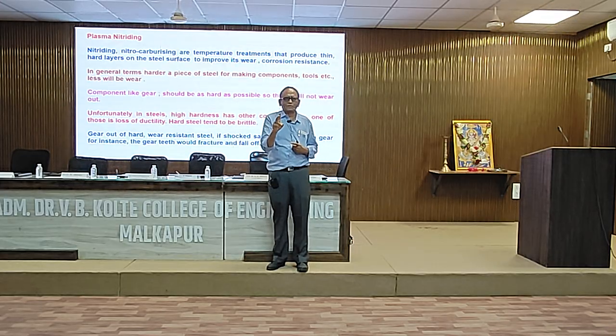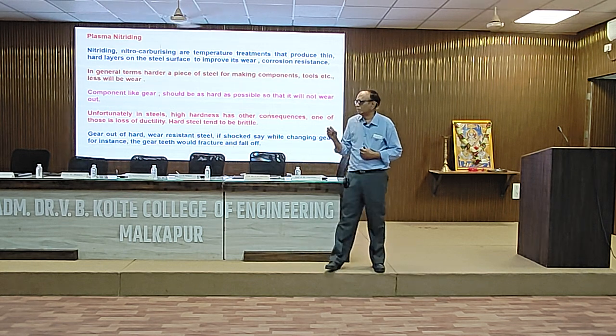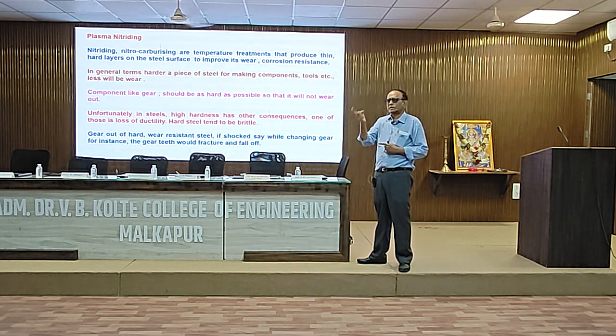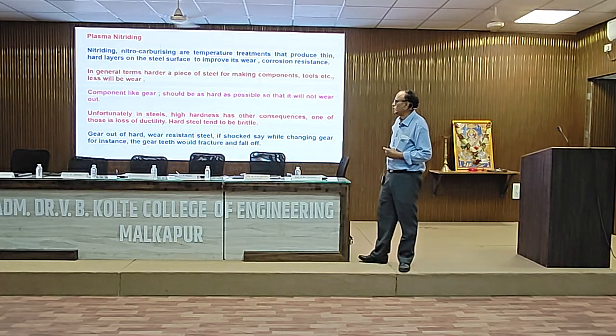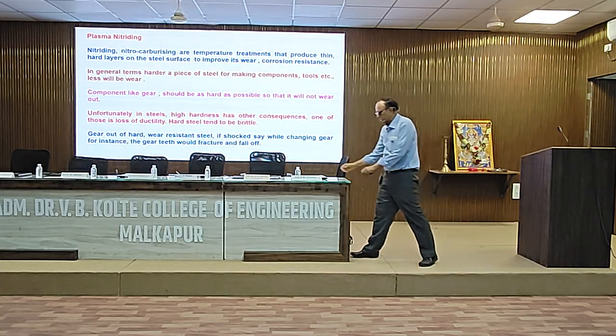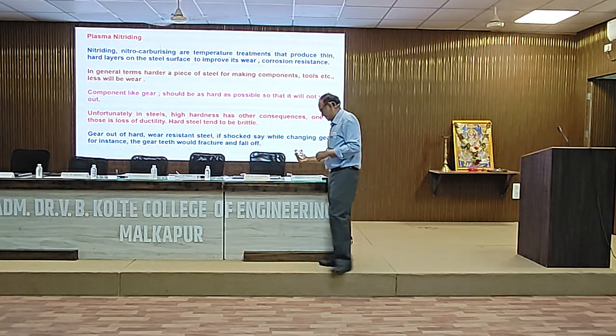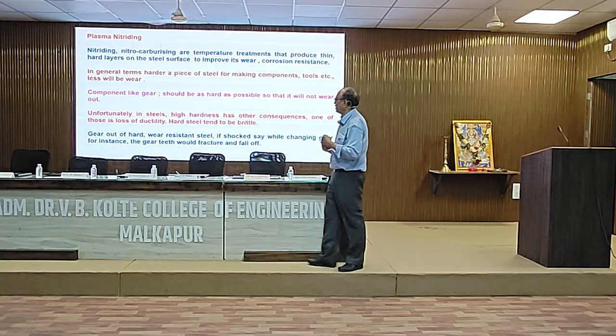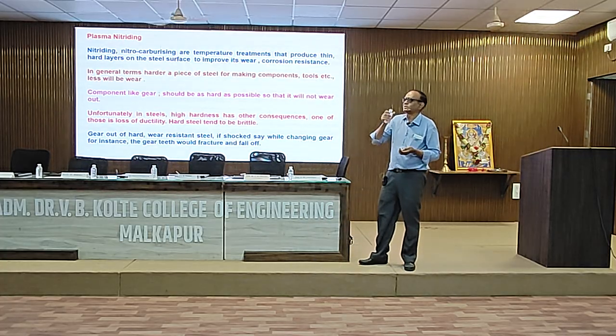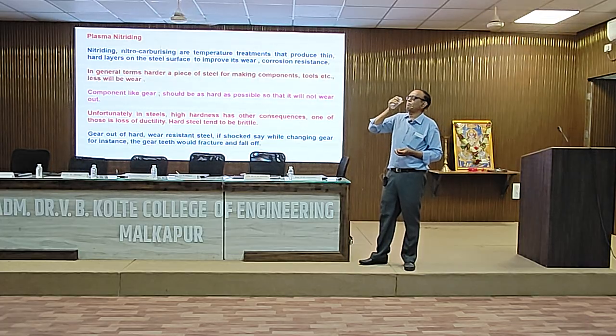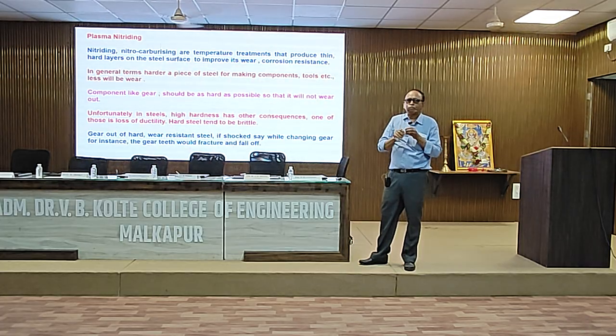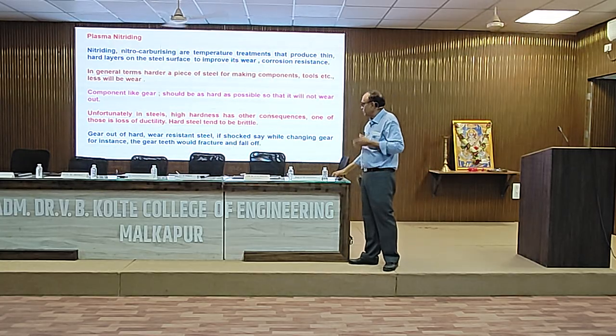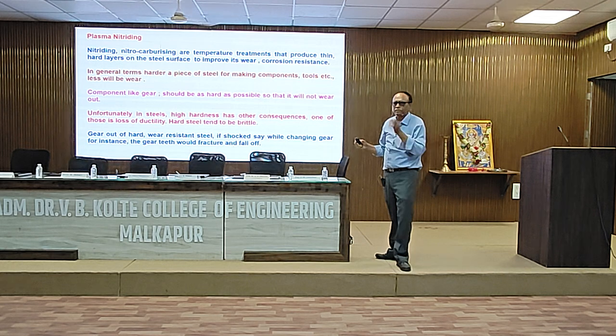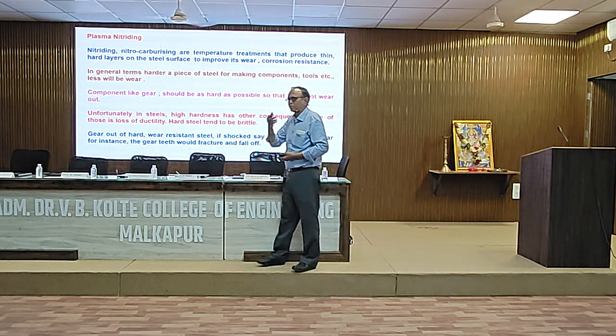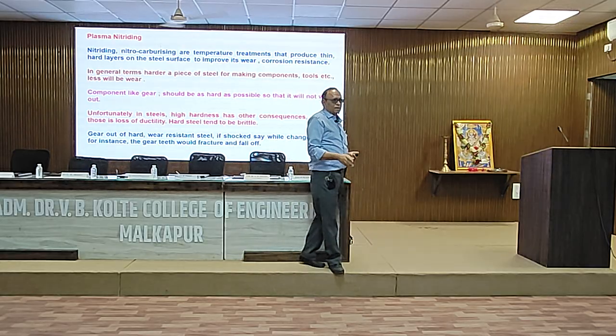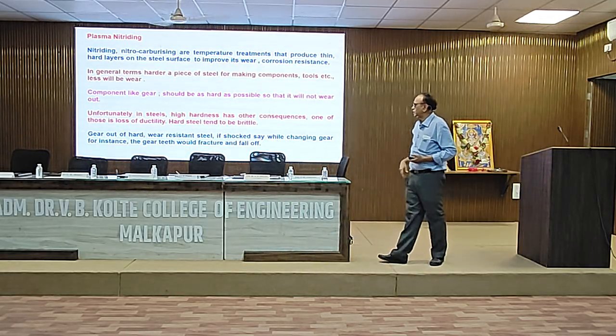See, steel has a hardness of 2 gigapascal, but if you can diffuse this nitrogen into that steel matrix, it can give you hardness up to 10 to 12 gigapascal, depending; at least 8 gigapascal is the minimum. Now, you will ask me, what is the use of this nitriding? Yes, nitriding has a very large number of applications. I will tell you just one example, the automobile industry. Like you have gears, you are using these car gears continuously, and so they undergo wear and all those kinds of things.